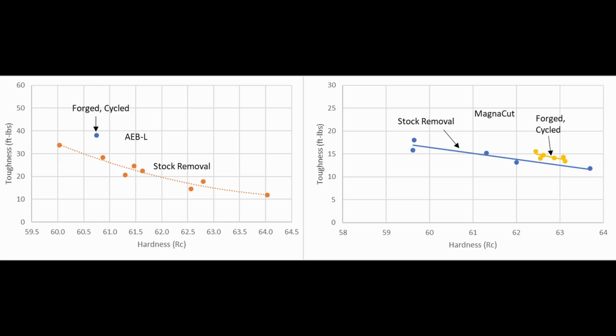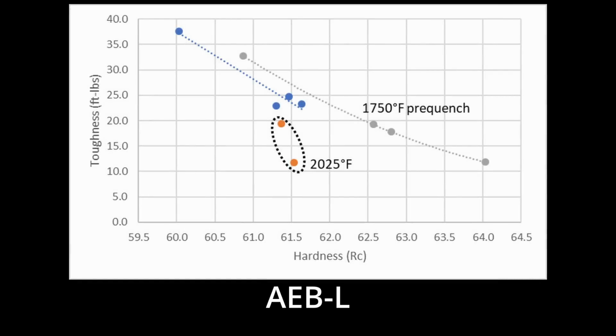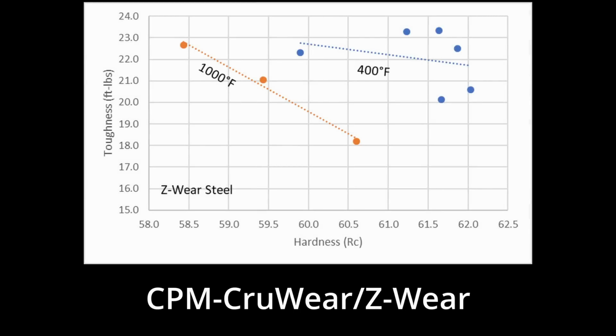In many cases, the difference is pretty small between a basic heat treatment and one with more involved thermal cycling. Usually with more complex and dialed-in heat treatments, the potential improvements are small, on the order of 10 to 20%. When I refer to dialed-in heat treatments, I don't only mean optimizing thermal cycling, but also optimizing the austenitizing temperatures and the tempering temperatures. I have many articles on my website and some videos for various steels, such as when I found that CPM Cru-Wear has better toughness with a low temperature temper of 400 degrees Fahrenheit or 200 degrees Celsius, despite the fact that the datasheet recommends the high temperature range of 1000 degrees Fahrenheit or 540 degrees Celsius.